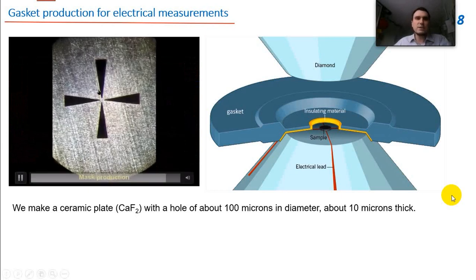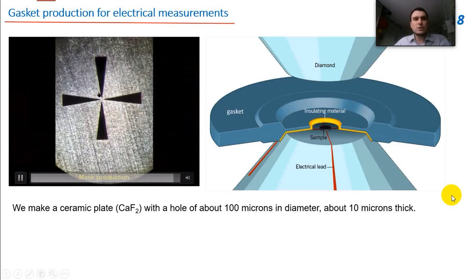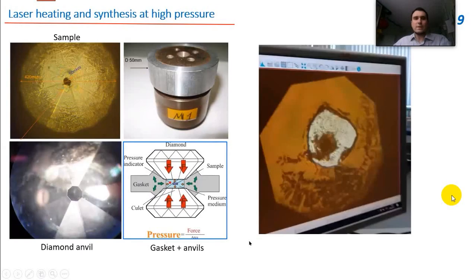The next stage is preparing the electrical leads. It's possible to do this using lithography or just deposition through a physical mask. On the next series of pictures, you can see the sample already heated. This is exactly the polyhydride already synthesized. It's a black material, with properties similar to a metal. And this is the diamond anvil and the culet. As I said, it's the plain top of the cone-shaped diamond, where exactly the chemical synthesis will go on. And this is the diamond anvil cell already prepared, compressed, and ready for experiments.